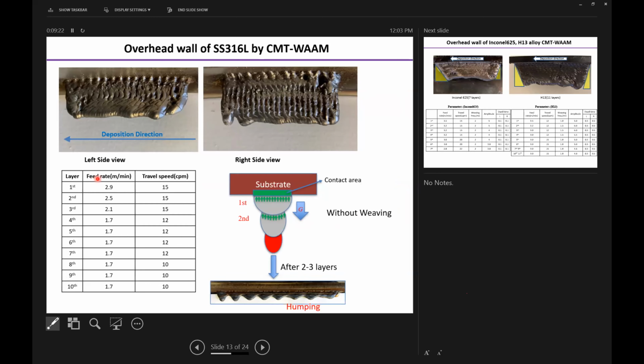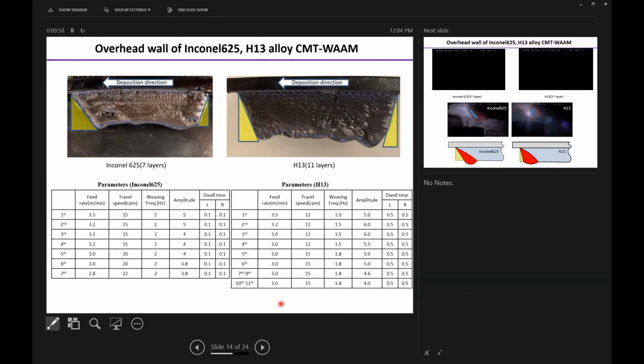Now after that we started with the deposition of the overhead wall. So here we can see the overhead wall of SS316L. These are the various deposition parameters, with a feed rate started for the first layer at 2.9 and a travel speed of 15. We used the weaving tool path because without weaving, after 2 to 3 layers, a humping defect was forming, and due to that we were not able to make a wall of good height. So that's why we use the weaving path for tool movement.